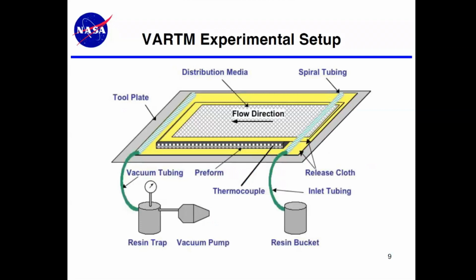This is a setup of VARTM, vacuum assisted resin transfer molding. The way the process works is there is a composite preform that's shown as an arrow pointing from preform into the diagram. There's a dry composite preform, usually stacked layers of fabric material placed on a tool. There is what's called a flow media that is cut to lay over top of the preform itself, with about an inch or two gap between the outside of the preform and the flow media itself.